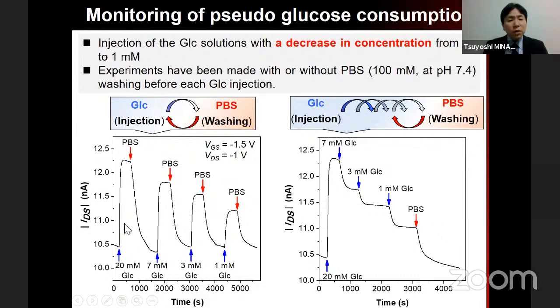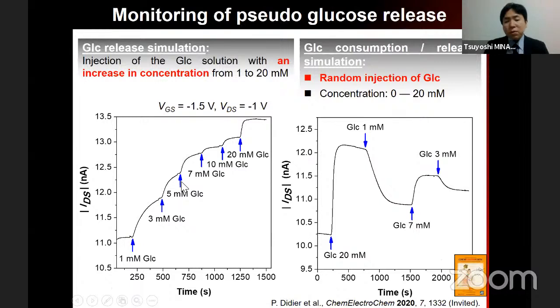The changes of drain current totally depend on the glucose concentration. When we gradually decrease the glucose concentration, the drain current change depends completely on it. So we can observe continuous and gradual change. We also observe it with a gradual increase of glucose. And with random injection, because cell activity is sometimes quite random, even with random injection of glucose we could continuously monitor the concentration. So now we are trying to monitor the activity of liver cells. Hopefully we can report it in the near future.